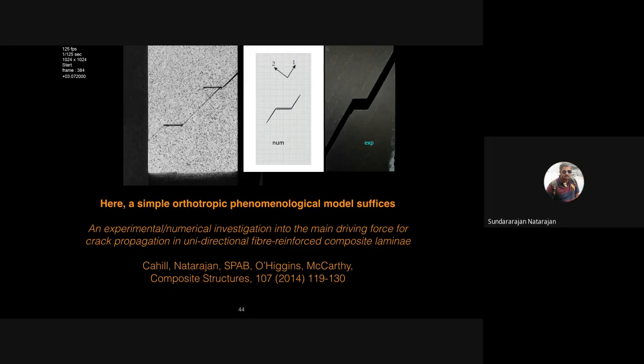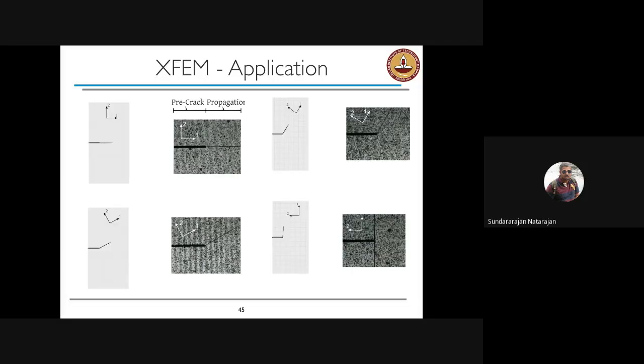And so we are able to model the crack growth in this orthotropic material using XFEM, and that closely matches with experimental results. So these are other configurations that we have modeled where the fiber is oriented along one direction. In this case, for a uniform tension, the crack is expected to grow straight as expected. For the other direction, you can see that the crack goes along the direction of the fiber.